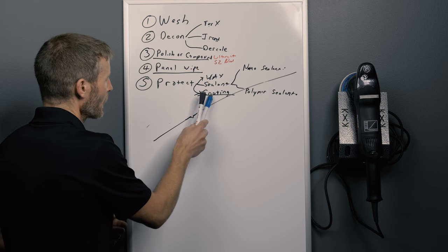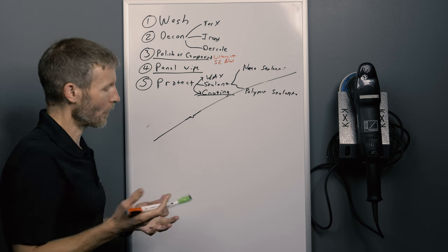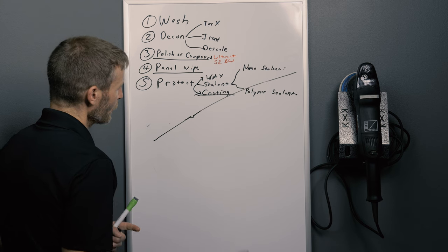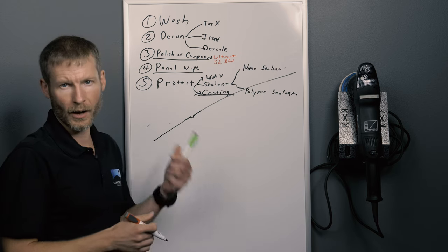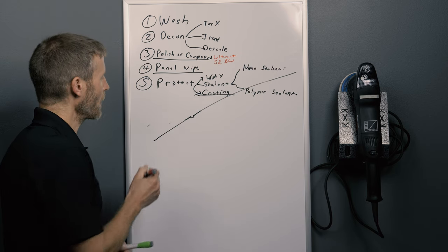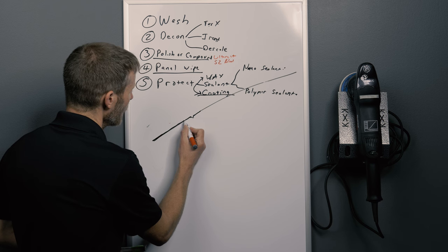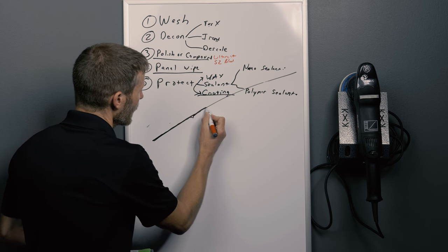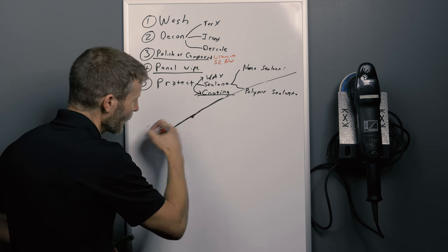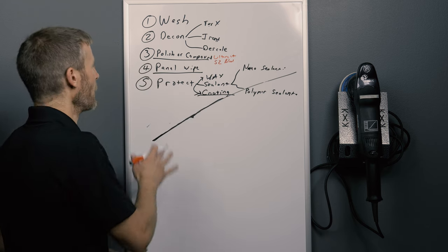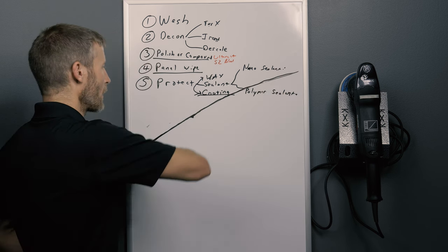So now we're going to put a ceramic coating on it. We've panel wiped it. We've decided we're going to use a ceramic coating long ago. And so when we put a ceramic coating on it, basically what happens is you have a bottle of product. We'll say C-Quartz UK 3.0. You put that on an applicator and you just apply it in a crisscross fashion. You can check out our other video for real close details on that. But that's going to put a layer. You can see how to do it in our other video. But that's going to put a layer of ceramic coating. Maybe a micron thick across there. And it's going to fill in that. And in a perfect, in reality, if you really zoom in on this, nothing's perfectly flat. You have pores in the surface. But this is as good an example to try to simplify it as we can make.